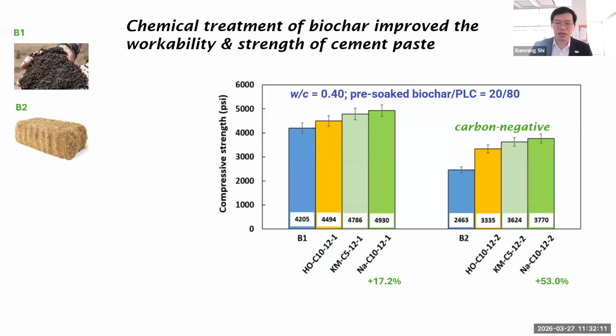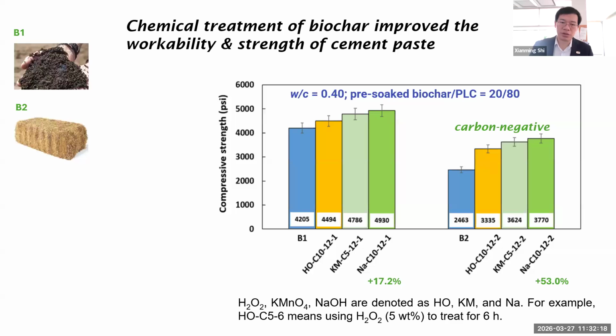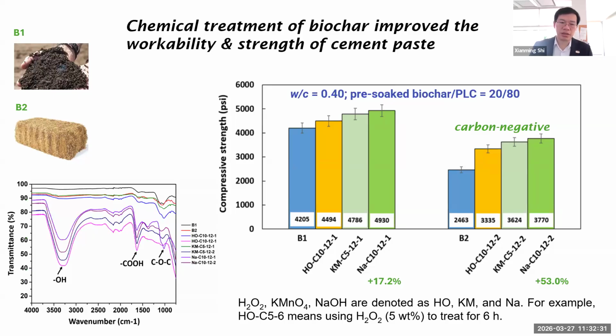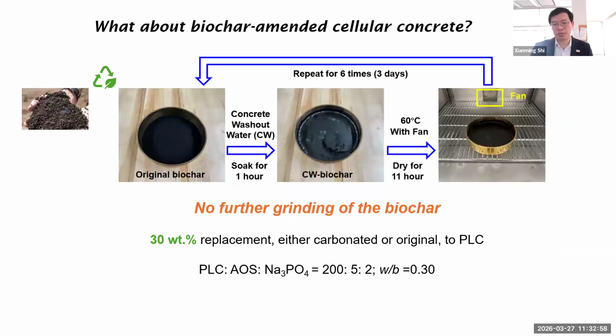So the good news is, in some cases, yes, we are able to achieve improvement in compressive strength at 28 days. And the most effective one seems to be the one using 10% sodium hydroxide treating the biochar for 12 hours. We also did the FTIR, Fourier transform infrared spectroscopy, and it basically shows our hypothesis was true, that we did induce the formation of hydroxyls and carboxyls or even ether groups on the surface of the biochar. That's why they worked better, and they chemically reacted with the cement hydration products, basically.